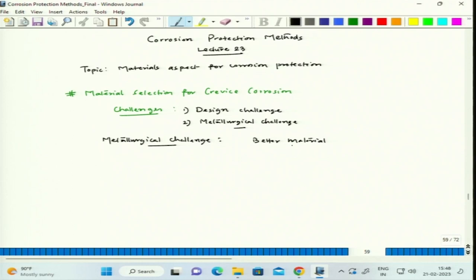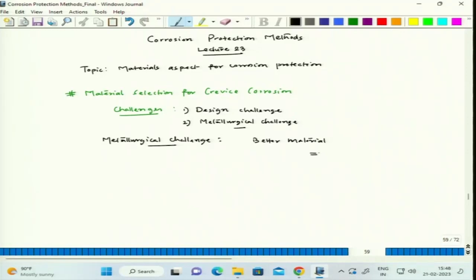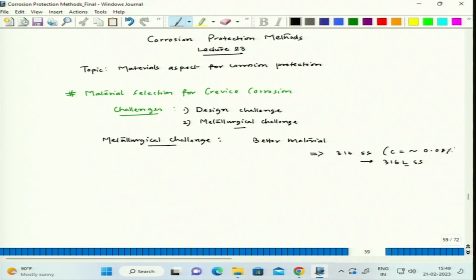The material which shows very good pitting resistance, for example 316 stainless steel — austenitic with molybdenum of around 3 weight percent — can give fairly good crevice corrosion resistance. For a better crevice protection we can go to 316L stainless steel, meaning low carbon. In 316, carbon content could be around 0.08 weight percent, while in 316L it is around 0.03 percent — low enough to avoid chromium carbide formation.